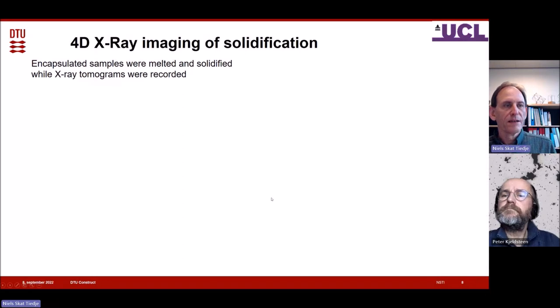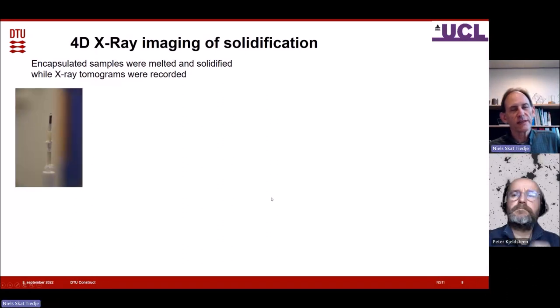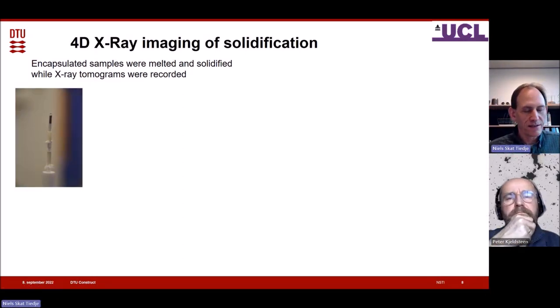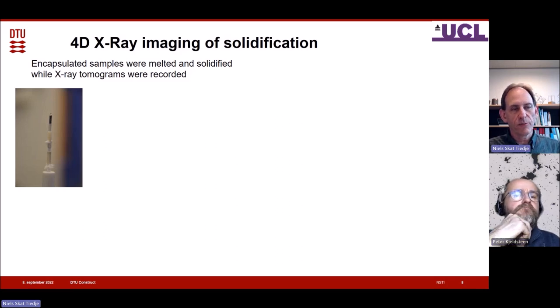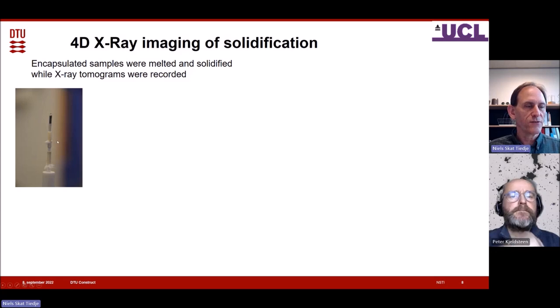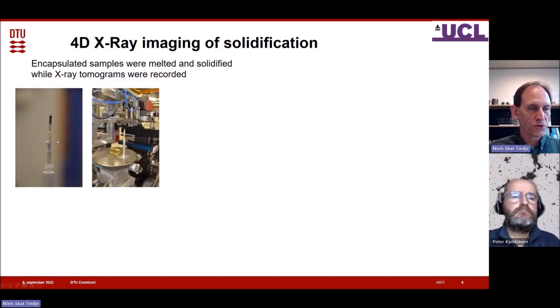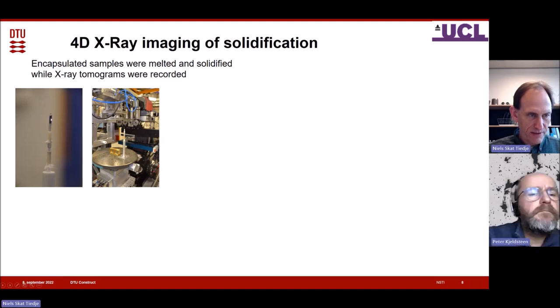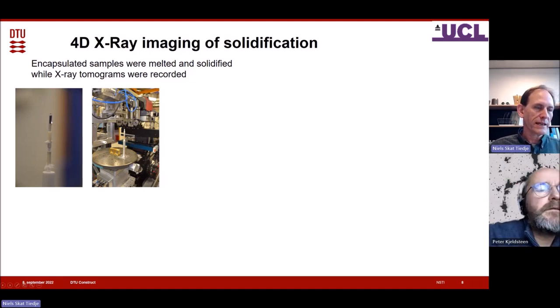Here we go. So the problem with X-rays is that when they hit metals, they are either reflected or slowed down. So if you have too much metal, the X-rays will not penetrate, and you may not get proper resolution. And we're talking resolution down to less than 5 micron. So we make very small samples. This is cast iron, 2 millimeters in diameter and 8 millimeters maybe in length.